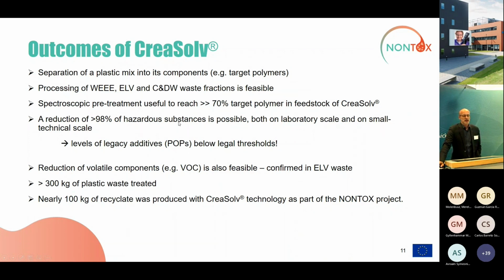If we look into the hazard substance reduction, we at least reached a level of 98%. If it's only 98%, mostly we had issues with detection limits in the recycled materials. So we claim that it's higher than 98 and guess it's even higher than 99. If we look into the legacy additives in the recycled materials, they were all below the legal thresholds, the current one and the new ones. Reduction of volatile components was also investigated with our CreaSolv materials. And here we could see it is clearly feasible to reduce them.